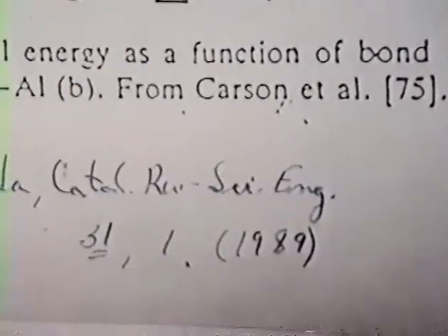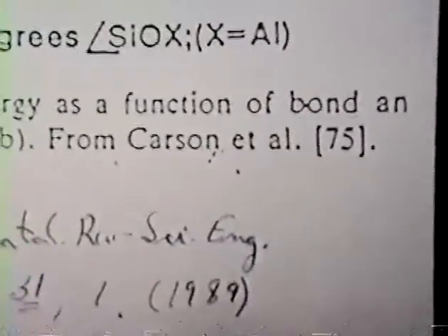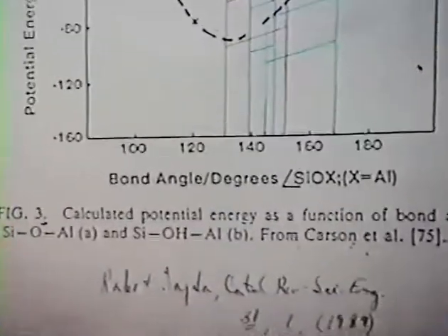And yet, L does seem to be unique. You can try other zeolites that you might think would be similar, and they seem not to be. So the question is, what's different about L? Well, it's different in a lot of ways if you compare it to something like Y, because that has three-dimensional channels, and L is a set of parallel channels, though the size of the openings and cavity are not substantially different. But another way it probably is different is that it appears to be more basic.